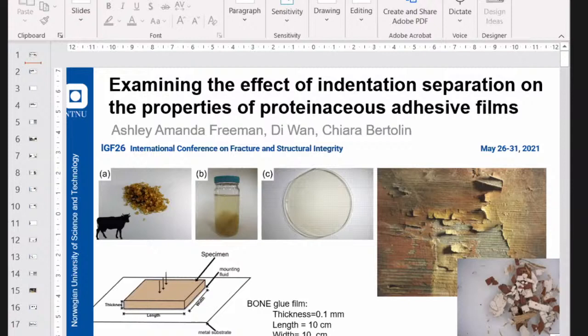These types of materials, because of ethical reasons, we can't sample in large quantities. So typically we have sub-millimeter size samples, as you can see in the lowest image. So the idea here is to test these adhesive films at the same length scale, by indentation, as the distemper paint, or the paint that is bound in these types of adhesives.